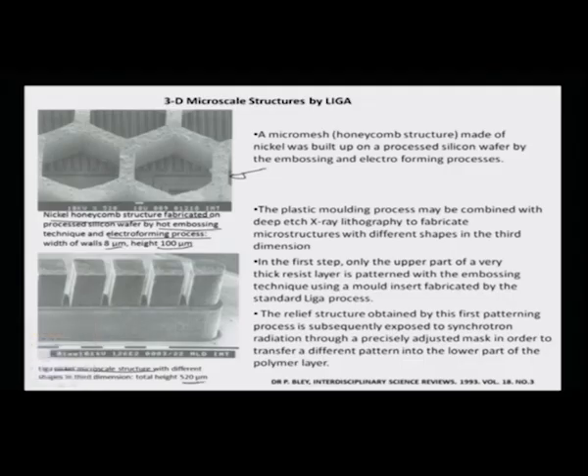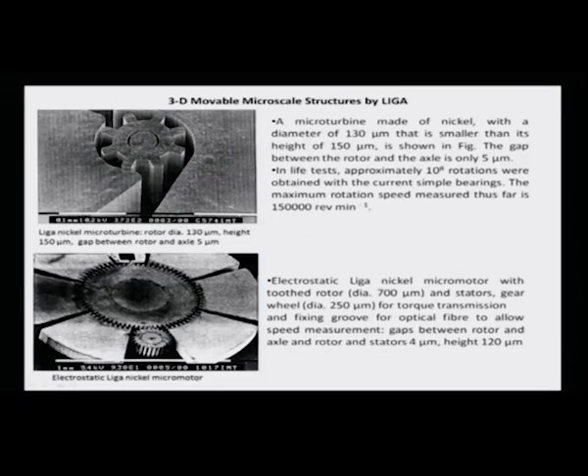520 microns. Similarly, there have been reports made by Bley et al. about different electrostatically made LIGA nickel micro motors or micro turbines, as can be seen very clearly in these figures, where the diameter of the micro turbine in this case is only about 130 microns, and the height is about 150 microns, higher than the diameter. So it is a small diameter, high aspect ratio structure. If you test this turbine, it can generate about 10 to the power of 8 rotations. That is the lifetime of this turbine, and the revolution it can go up to is very high, in the range of about 150,000 RPM.